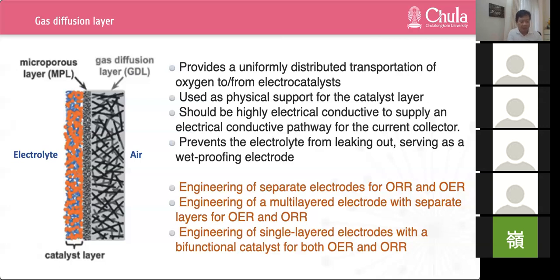Hydrophilic microchannels are properly wetted for providing access to the liquid electrolyte. The hydrophobic microchannel counterparts are designed to facilitate fast air diffusion from the atmosphere to the catalytic site and to provide a barrier to prevent electrolyte penetration. The battery polarization behavior in terms of electrical conductivity, ohmic resistance, and gas permeability mass transfer are influenced by the degree of hydrophobicity in the GDL.